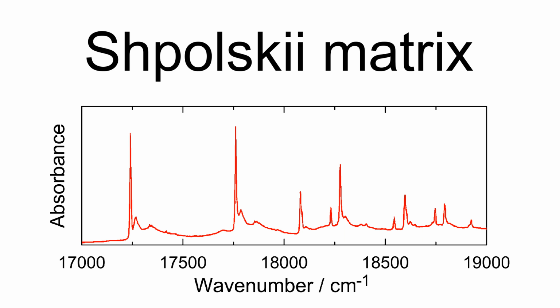The weak coupling is usually expressed in terms of the Debye-Waller factor, where a maximum value of 1 indicates no coupling between the chromophore and the lattice phonons. The narrow lines characteristic of the Shpolskii systems are only observed at cryogenic temperatures because at higher temperatures many phonons are active in the lattice and all of the amplitude of the transition shifts to the broad phonon sideband. The original observation of the Shpolskii effect was made at liquid nitrogen temperature, 77 kelvins, but using temperatures close to that of liquid helium, 4.2 K, yields much sharper spectral lines than is the usual practice.